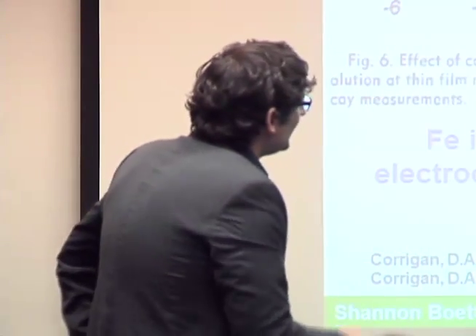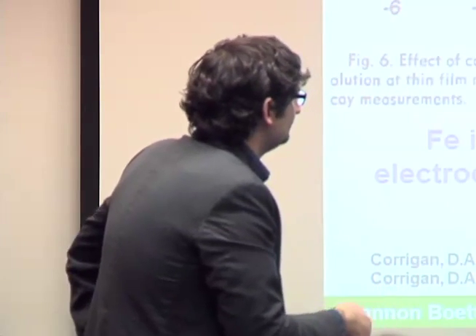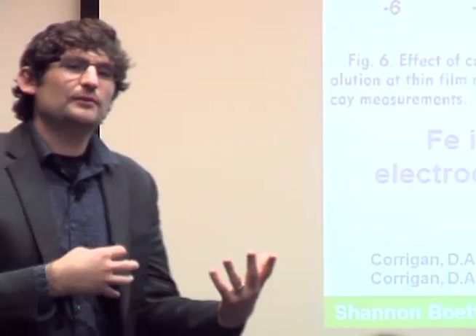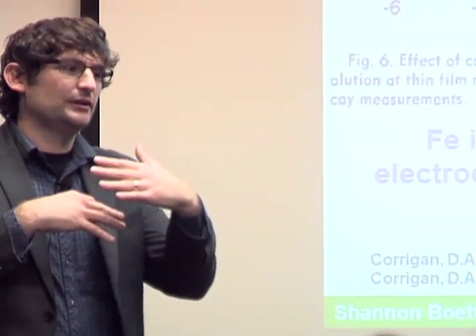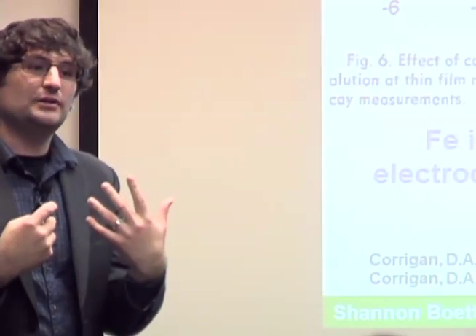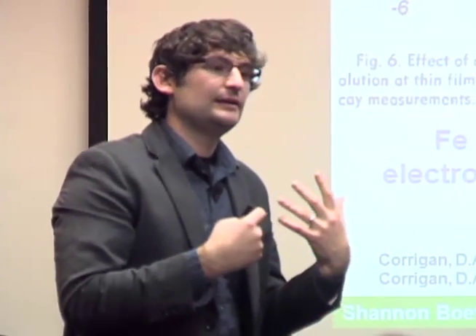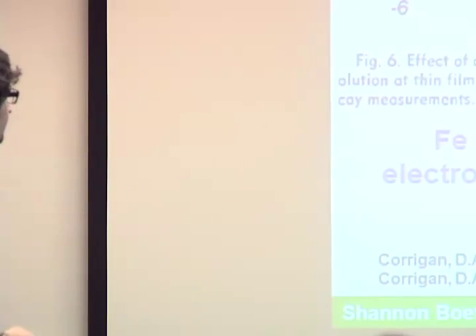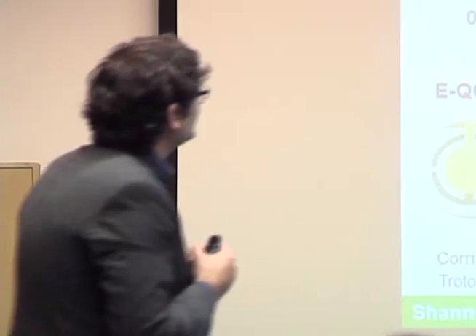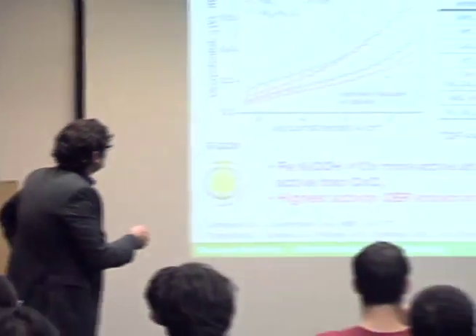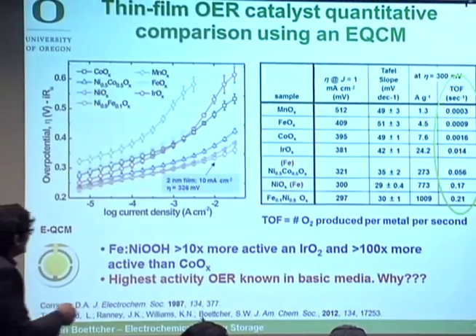So we went and looked in our films, and sure enough, they all had iron in them. Not only were we converting from a crystalline material to a layered material, it was reacting with the electrolyte, pulling iron impurities out of the electrolyte that were getting incorporated into the structure and changing its activity. Okay, so this is going to be really important in a second. We did this type of careful study for a lot of different metal oxides. The surprising thing to us was that these nickel iron materials, any material that started out with nickel and either accumulated iron via reaction with the electrolyte impurities, or we put iron in from the beginning, had activities